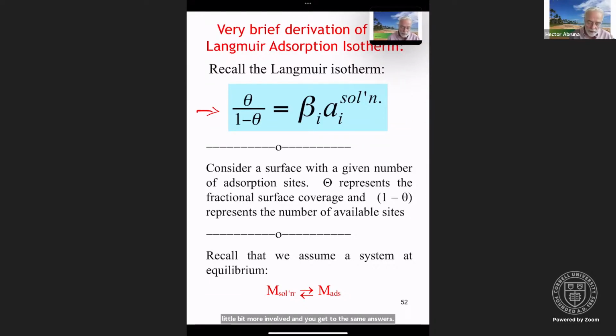So you consider a surface with a given number of adsorption sites. And theta represents the fractional surface coverage. That means how many sites are occupied, and obviously then 1 minus theta corresponds to the number of available sites. We assume a system that is at adsorption equilibrium, meaning the species in solution is in equilibrium with the species adsorbed. So we can write the rate of adsorption and the rate of desorption, and then we can equate those two. So what are those?